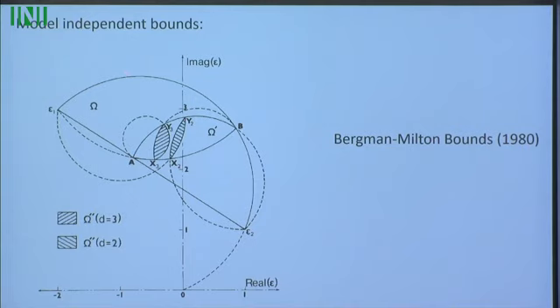And so back in 1980, myself and David Bergman obtained these bounds, which are sort of circular arcs in the complex plane, depending upon what you know about your material. And so epsilon 1 and epsilon 2 are the dielectric constants of the two materials. If you don't know anything about the material, then a diagonal element of the dielectric tensor necessarily lies in this large region omega, and this straight line just corresponds to a laminate of the two materials with the layers in the direction of the applied field, and this is a laminate with the layers perpendicular to the direction of the applied field. And then other geometries, if you know the volume fraction, you can restrict the region down to this one here.